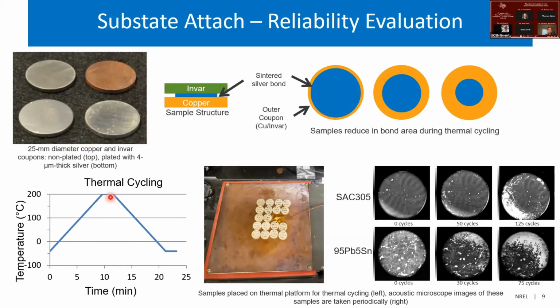temperature power electronics. Again, the temperature, and I'm not sure if I mentioned it, but worth mentioning again, it's an important knob to increasing the power density of the components, and hence the interest in higher temperature, at least for mobility applications. So these are the coupons on a hot plate, some of the cycling happening. We observe the interfaces under acoustic microscopy.